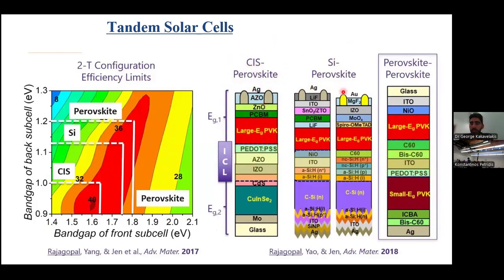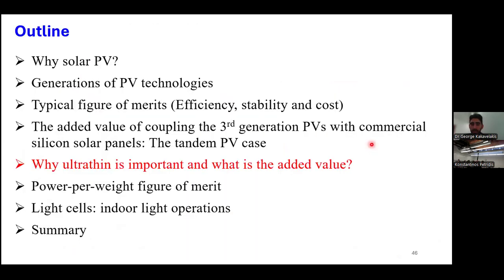And good news, we can also make low band gap perovskite materials. If we engineer the materials, we can make low band gap perovskite to absorb in the same ranges as silicon, and still use this wide band gap perovskite and make the so-called perovskite tandem device. As you can see here, the maximum efficiency these devices can produce is approximately 48%, as far as I remember. And so far, we have managed to achieve 30% in the literature. So also this direction is going very well. And the perovskite material is an enabler for high efficiency tandem devices in order to break the efficiency limit.